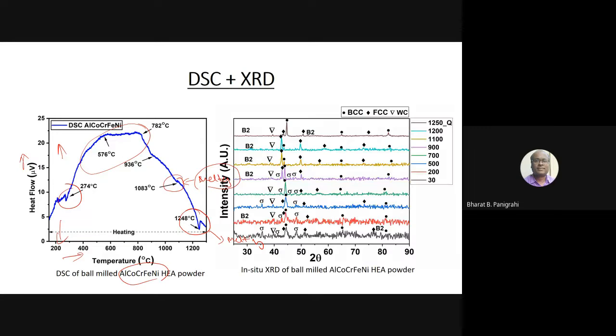If you look at the X-ray, these are the in situ X-ray where we actually heat and do the X-ray at high temperature. So we have an in situ X-ray diffraction machine where you can simultaneously heat and do it. I do not want to go into details about phase. What I want to say here is, whatever alloy you make, you can understand their phase evolution with the help of DSC. It will tell at what temperature, what kind of reaction is happening.